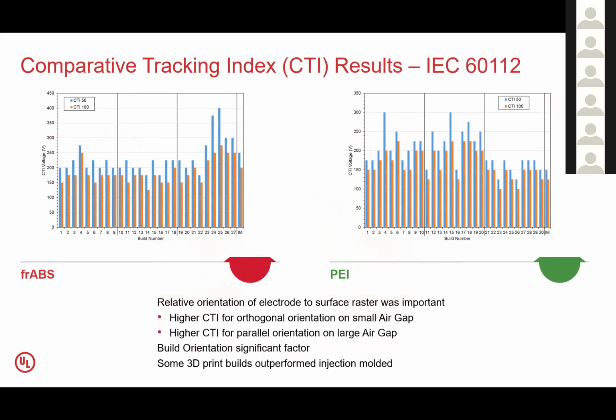So again, I'm plotting out our ABS on the left and our polyether imide on the right. Injection molding is on the right side of both of them, and then our 30 different variations of 3D printed samples. If we focus on the ABS to start with, we do see a difference, where you can see, again, the Z orientation, which is in the third box. We're starting to see some significantly higher comparative tracking index voltages, indicating better performance, but it is the same material in every case. And that's actually the opposite of what we saw with the polyether imide, where the horizontal ones in the X and the Y, the first two boxes, seem to be giving the better performance.